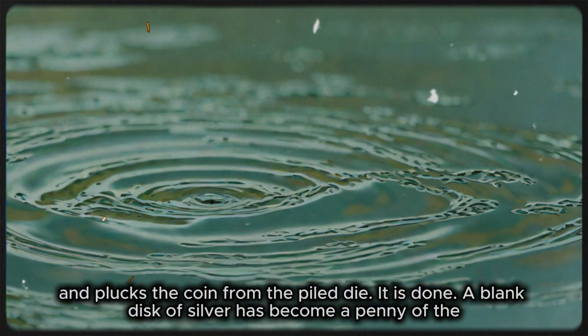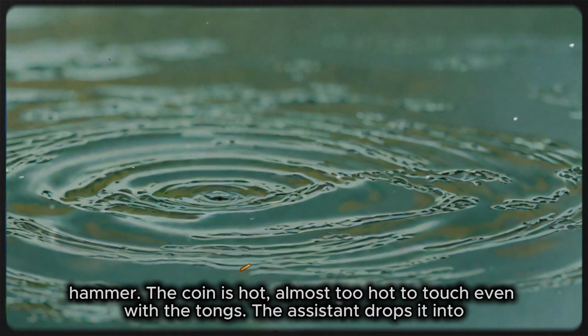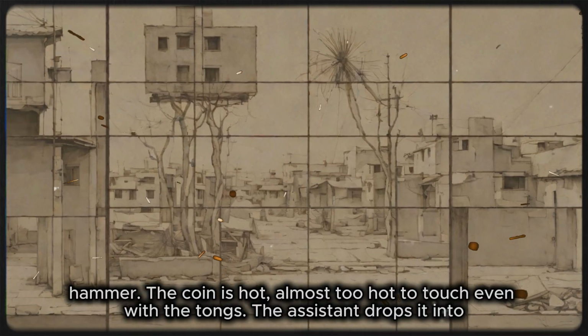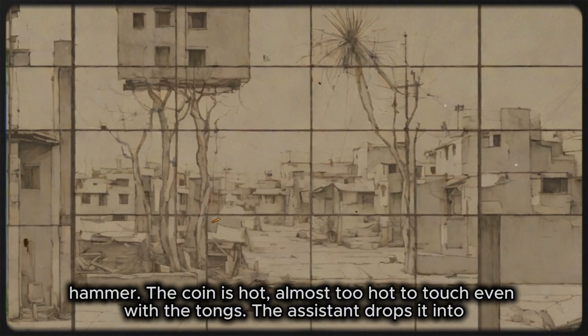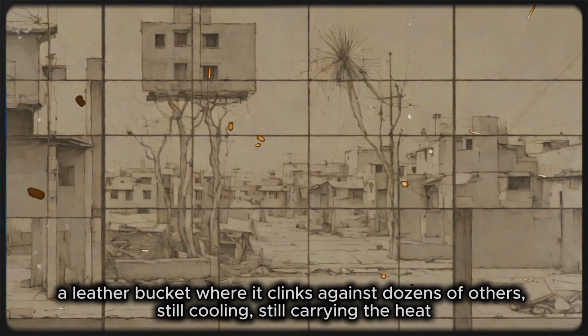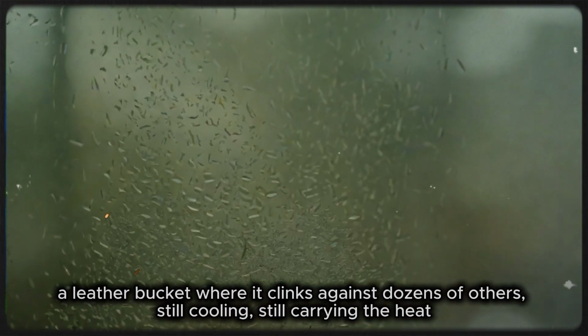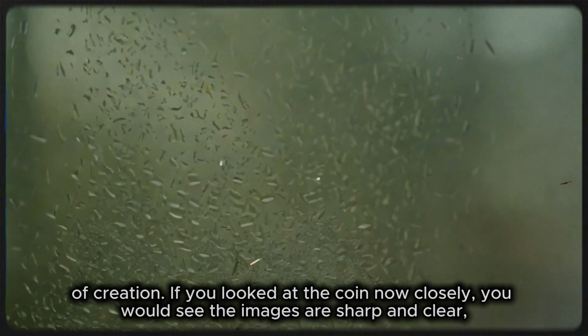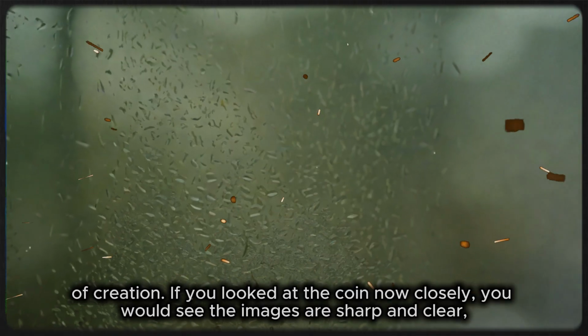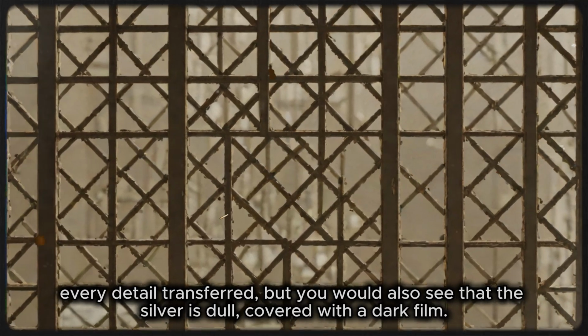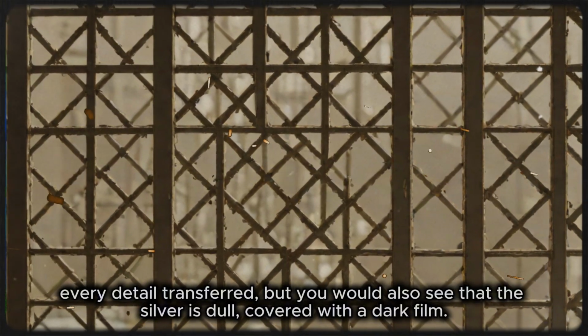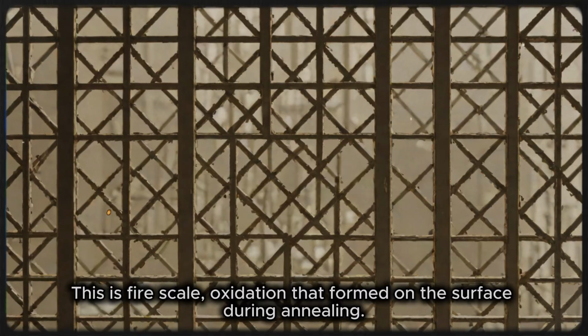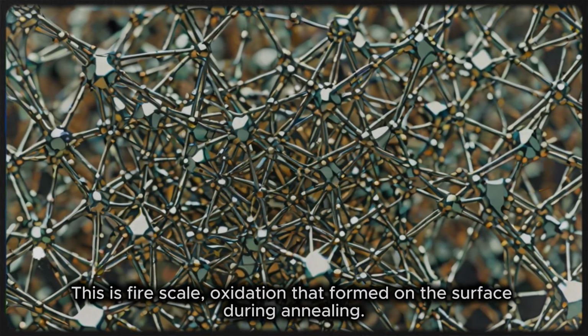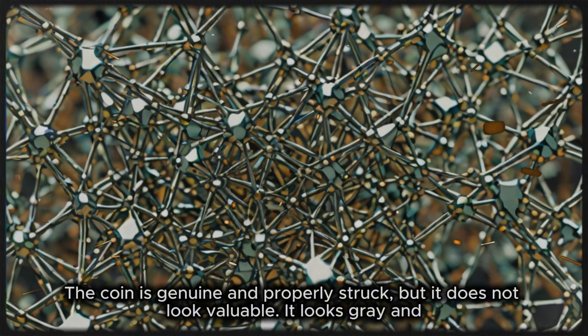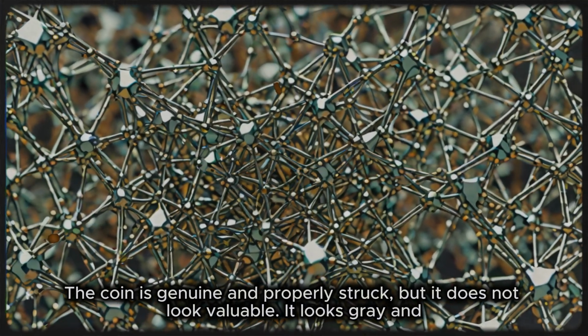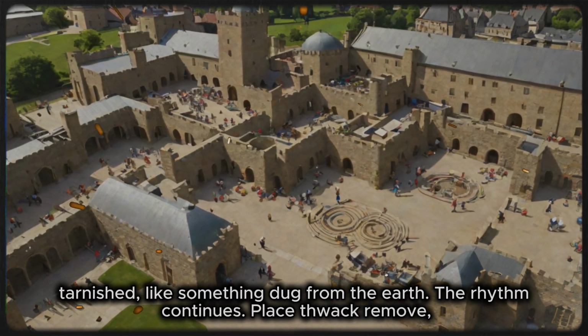The transformation took perhaps half a second from the moment the hammer began its descent to the moment the coin was lifted free. The coin is hot, almost too hot to touch even with the tongs. The assistant drops it into a leather bucket where it clinks against dozens of others, still cooling, still carrying the heat of creation. If you looked at the coin closely now, you would see the images are sharp and clear, every detail transferred. But you would also see that the silver is dull, covered with a dark film. This is fire scale, oxidation that formed on the surface during annealing. The coin is genuine and properly struck, but it does not look valuable. It looks grey and tarnished, like something dug from the earth.